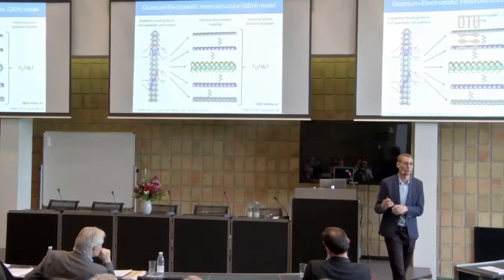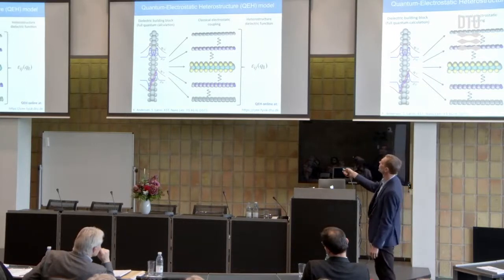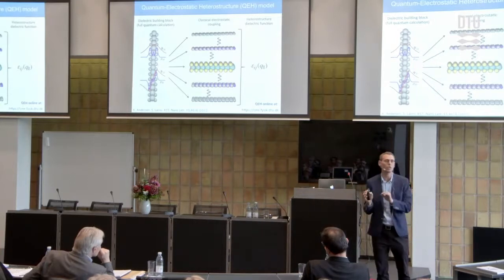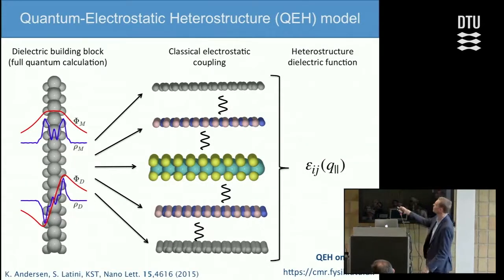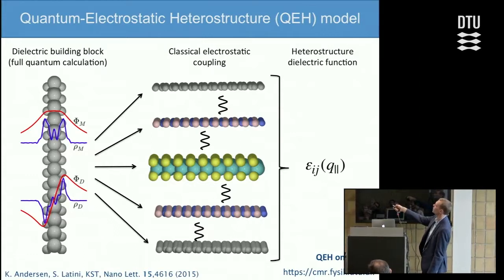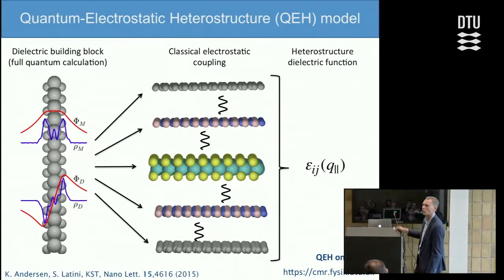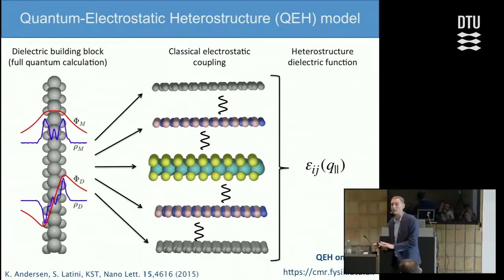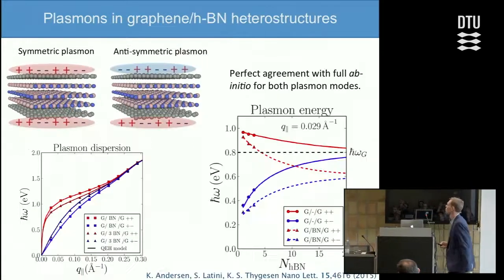We couple them together only by the Coulomb interaction between the layers. That's a classical coupling mechanism, and it enables us to calculate the full dielectric function of the material. With that, we can calculate the effective interaction between an electron located up here and another electron located down here. So we have full control over the dielectric properties of the heterostructure using this method.